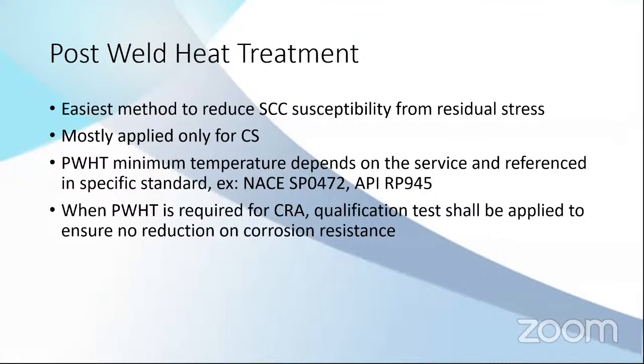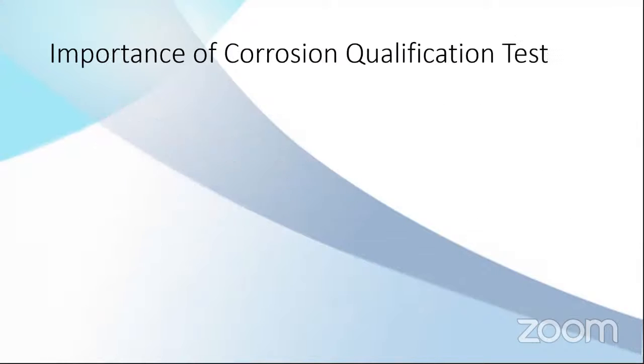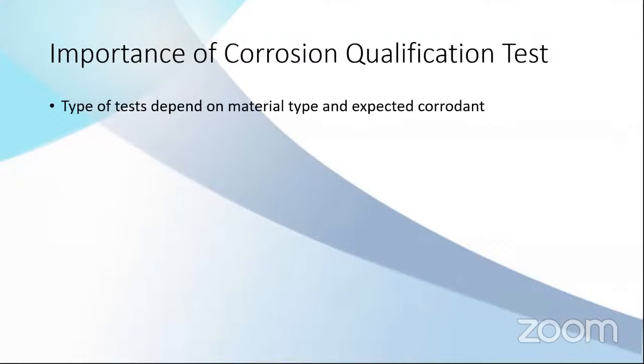The samples need to be corrosion tested to ensure that the application of post-weld treatment does not affect the corrosion resistance of the materials. If you don't do this, then it's possible that during service the stainless steel will get corrosion because of the sensitization. And that is why the corrosion qualification test is very important during the PQR.